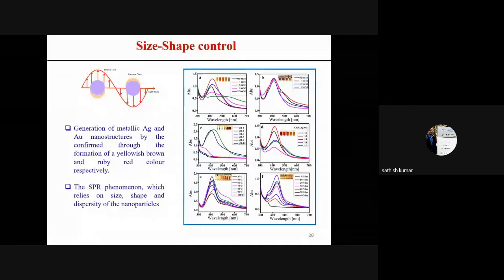So whenever we synthesize nanomaterials, particularly these optical nanoparticles, we need not go for high-end experiments like HRTEM, which is a costly experiment. So we can predict the size of the nanoparticles based on the color formation as well as the surface plasmon resonance, which is known as the SPR effect. This SPR effect is due to the collective oscillation of the electrons on the surface of the nanoparticles.